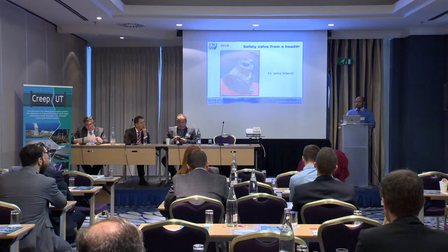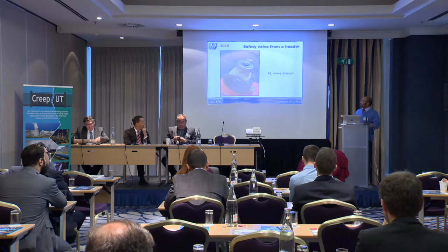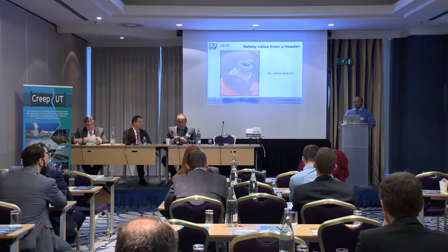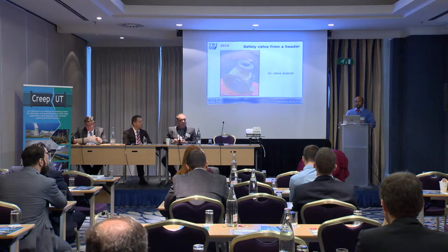And I have here an image of the component that we worked on, which is a branch weld, which had been in service for some considerable amount of hours. It was made of the kind of grades that Alex has been talking to us about. And what we had was a configuration of welds, which were termed set-on welds, which went around the nozzle and presented some problems geometrically for the inspection, which we had to solve before we could address the actual creep problem that was found.